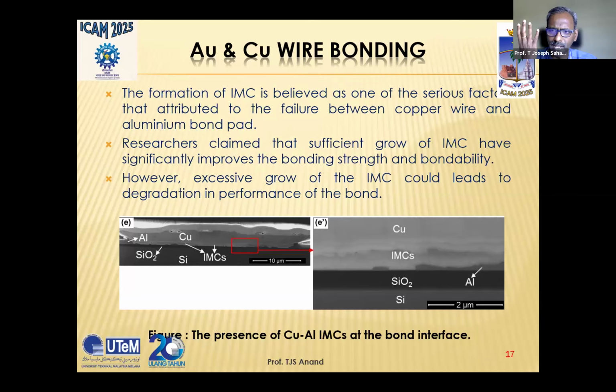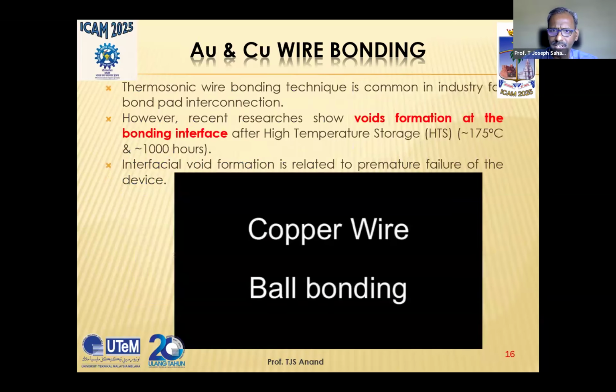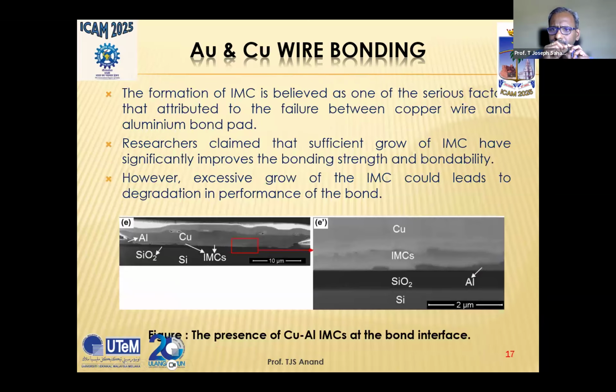So what is the problem here? When we replace gold with copper at a certain temperature, what we normally call industrial temperature, 175 degrees centigrade, with high temperature storage and a bonding time of 1000 hours, void formation takes place. A void is actually nothing but a bubble, a small gap. These are all real TEM pictures, transmission electron microscope pictures.